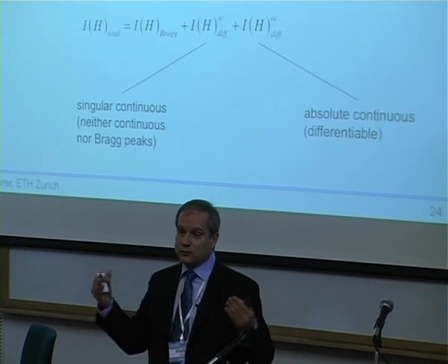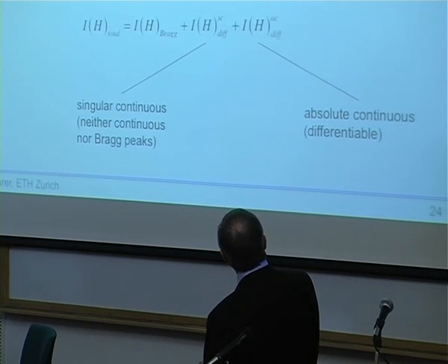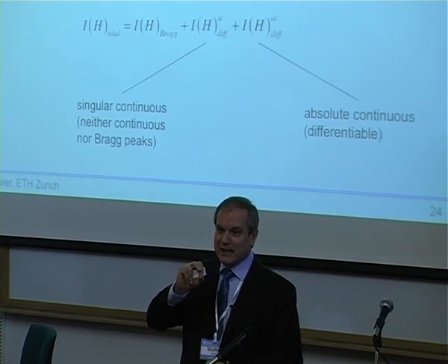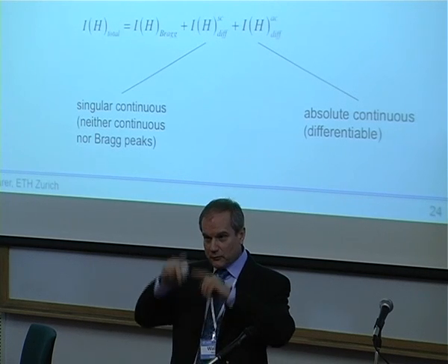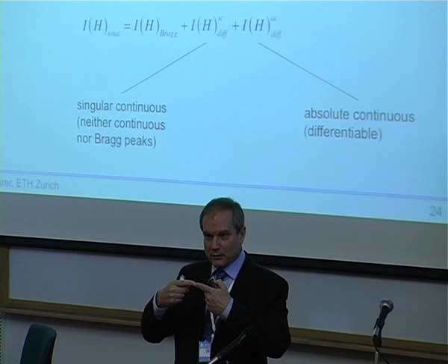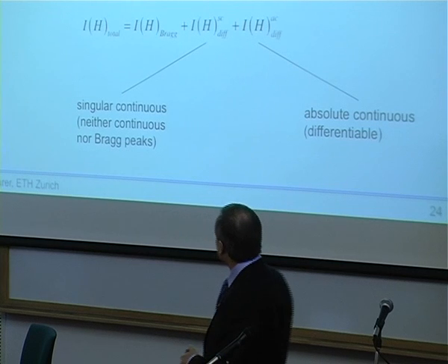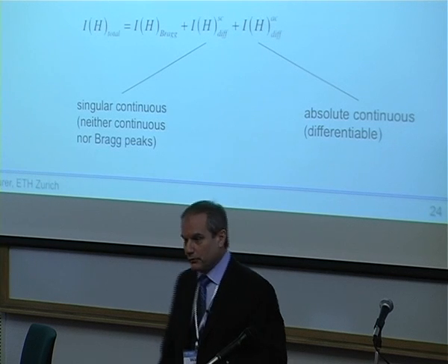To have a not too narrow definition, it was defined in the way that any solid having an essentially discrete diffraction diagram. You will see that the Bragg spots of a quasicrystal are densely distributed in reciprocal space. But the intensity differences between neighboring spots are extremely large, and therefore you see a discrete diffraction pattern, and therefore this fuzzy definition, essentially discrete. Okay, and an aperiodic crystal doesn't have three-dimensional lattice periodicity.